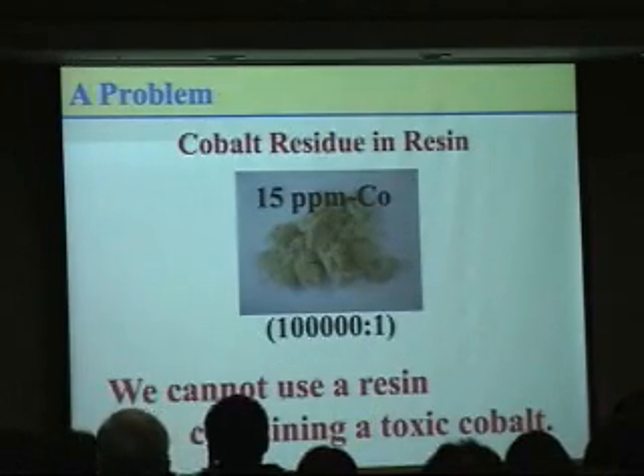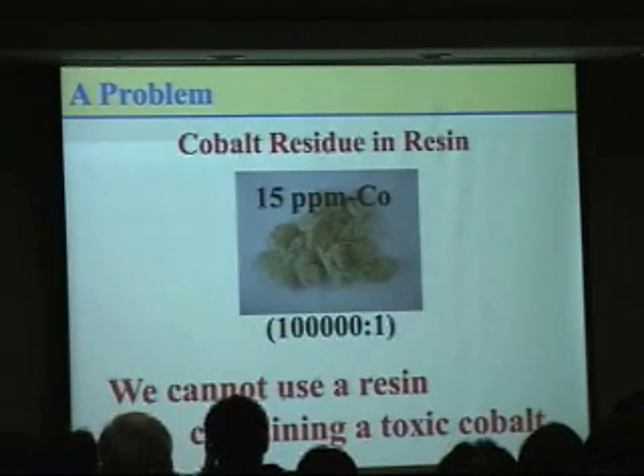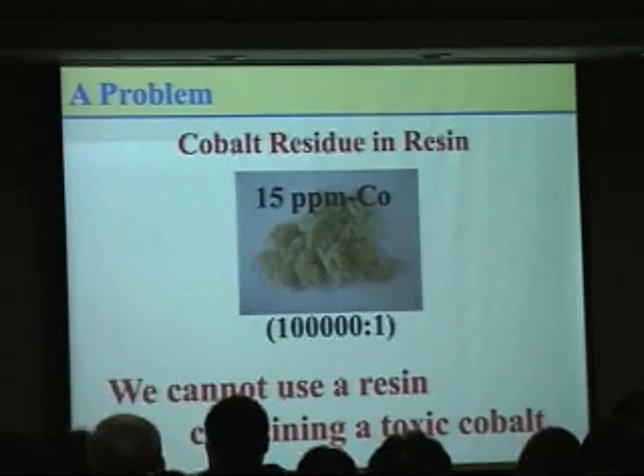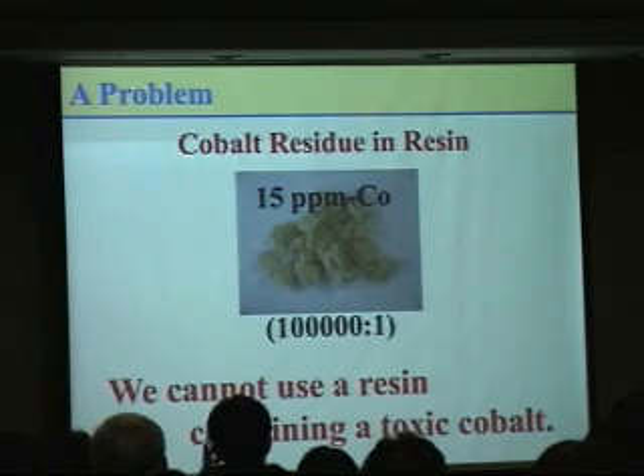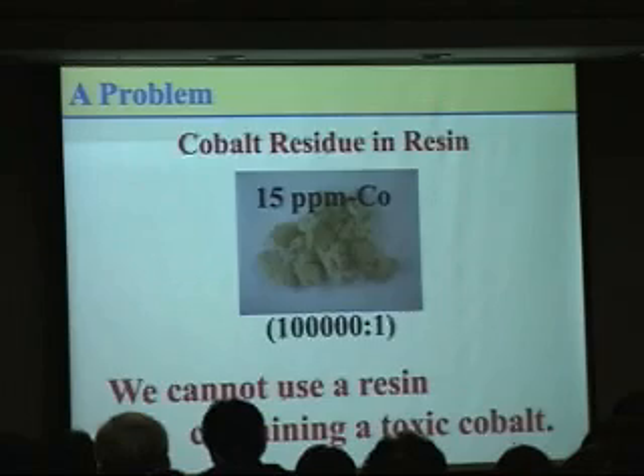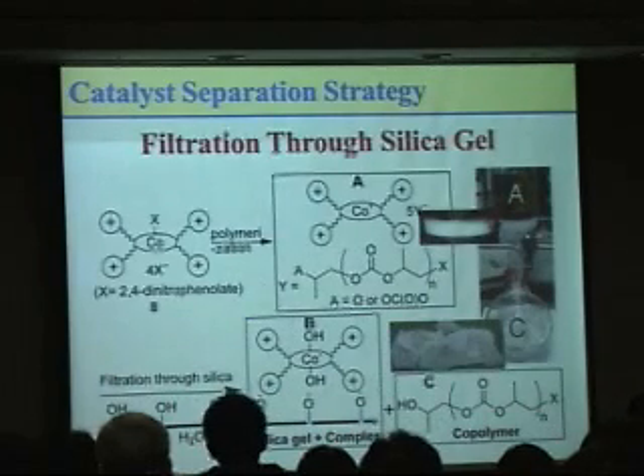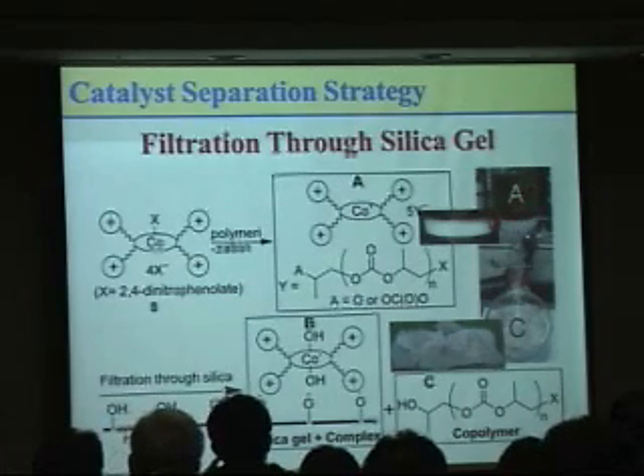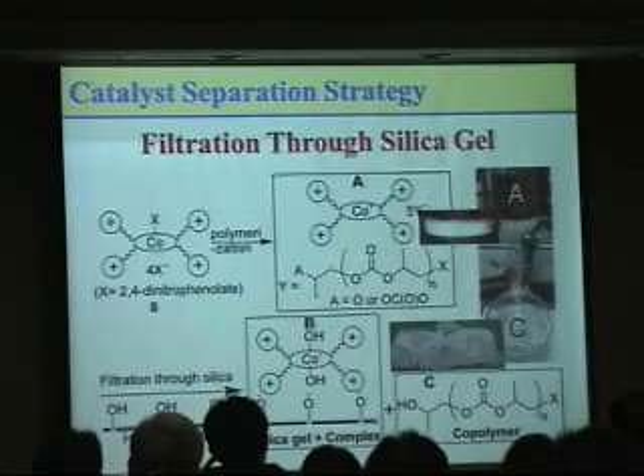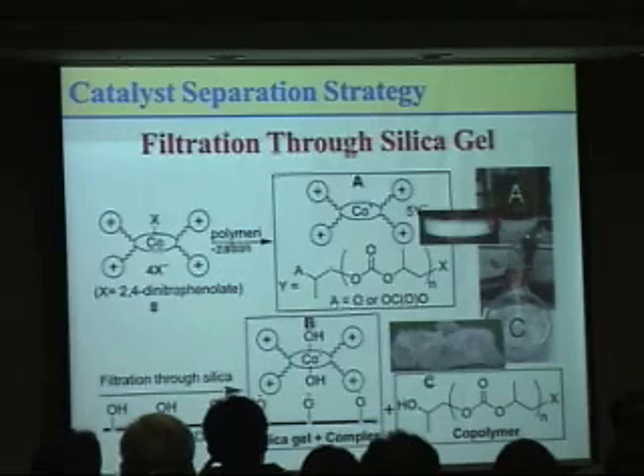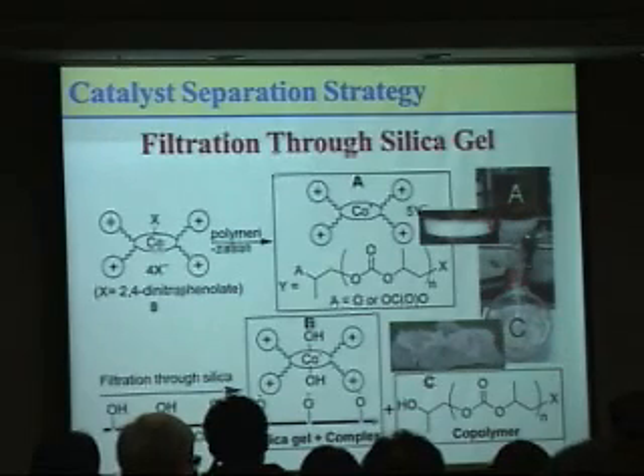So even though I have developed a very efficient catalyst, I still have one problem. The isolated polymer is yellowish like this because it contains cobalt residue. And cobalt is a transition metal, it is toxic, so we cannot use a resin containing toxic cobalt residue. So I devised a catalyst separation strategy. After polymerization, the solution is yellowish like this because it contains the homogeneous cobalt catalyst. When the polymer solution is passed through just a short pad of silica gel, the catalyst can be captured on the surface of the silica very efficiently, and the polymer solution is liberated as a colorless solution.